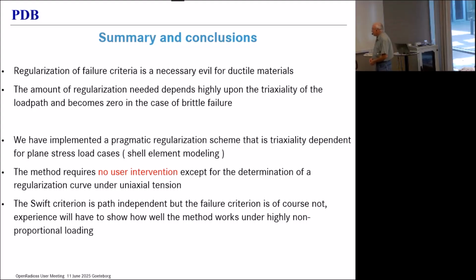Now, is it perfect? Of course not. Nothing is perfect. The Swift criterion is actually path independent. The failure criterion is not. We know that failure is quite path dependent. So we're combining something that is path independent with something that is path dependent. As long as you do proportional loading, it works, of course. But under highly non-proportional loading, well, application will show. Experience will show.